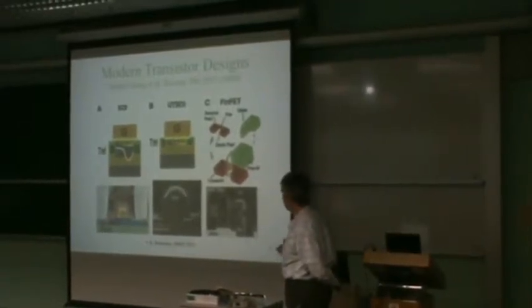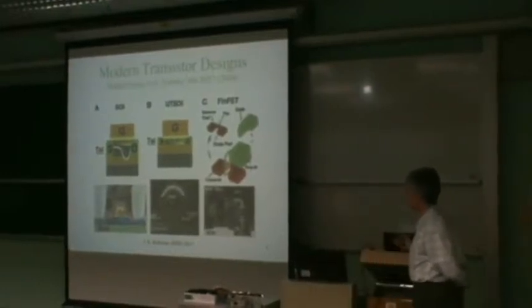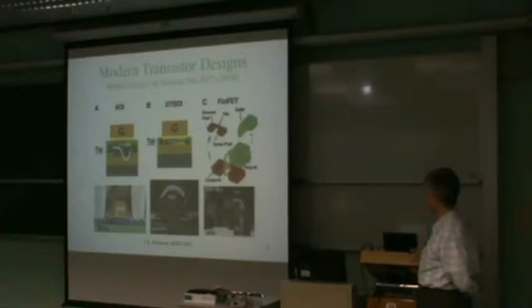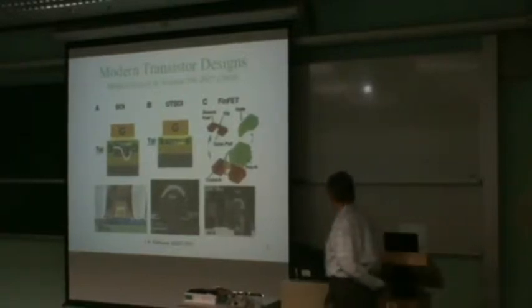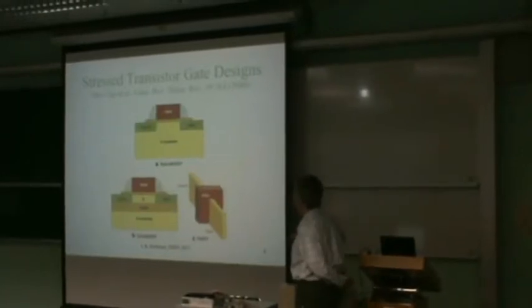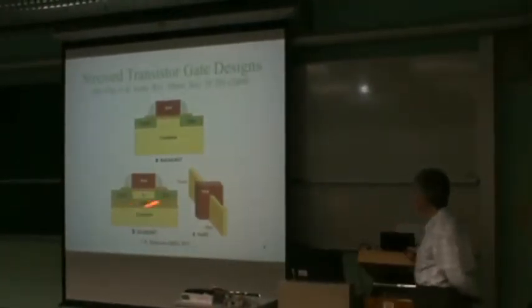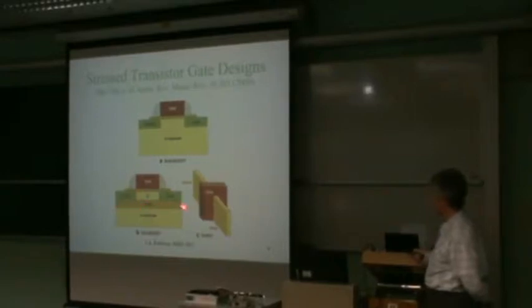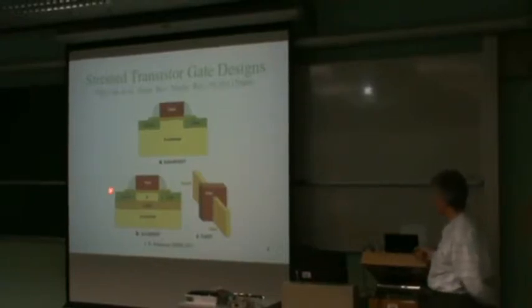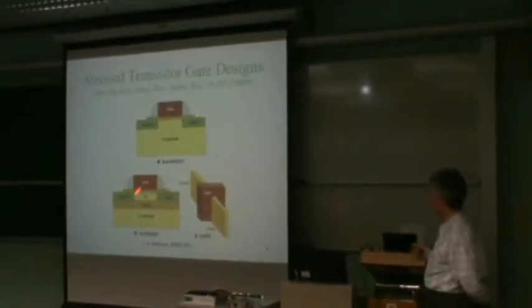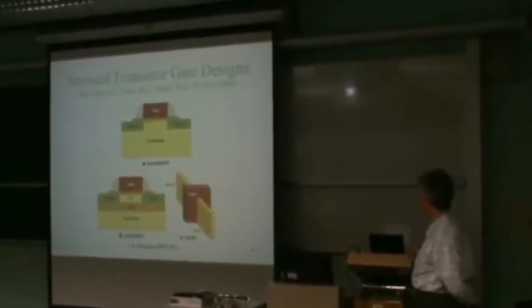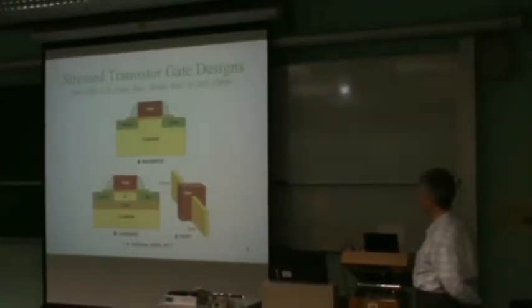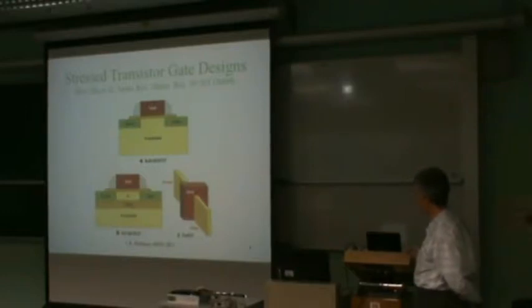So at the bottom are cross-sectional SEM pictures that have been colored to show the different regions in a real actual device for the three examples. I have another example here. And this is showing the SOI method where you put in an oxide layer and pattern your material, your channel, into an already thin silicon layer, which is wafer bonded onto the substrate, and then you put in your stressing structure above with the gate sitting above the device, or the more conventional standard MOSFET configuration with the stressing arrangement, and then the FinFET once more.